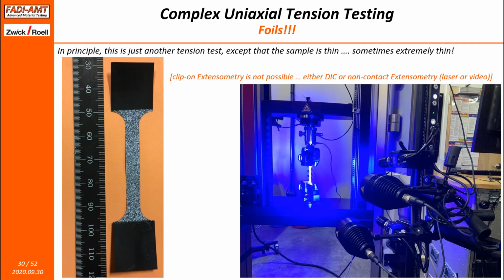Now, in principle, there's nothing really different between testing a foil and a sheet. It's the same machine, and to some extent the same grips, and so on. The only difference is that the sample is really tiny or thin, in some cases extremely thin. I'm showing a picture on the left-hand side just to give you a sense of it. This particular foil wasn't really difficult to deal with because it was 50 microns, so that's considered okay. Sometimes we have lower thicknesses.